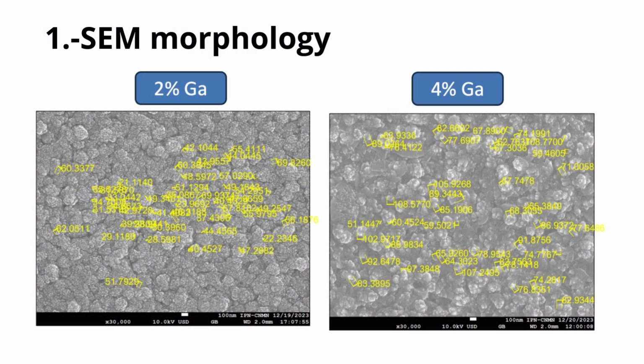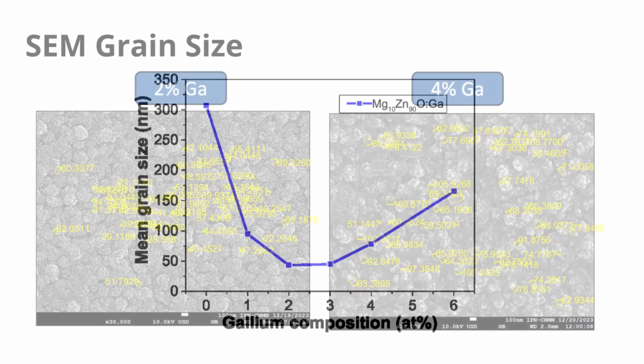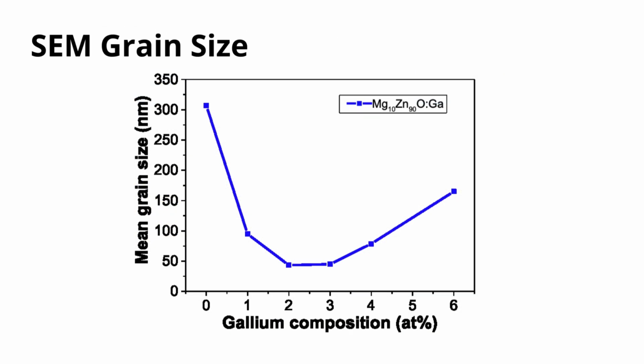The first step of characterization is SEM. SEM morphology. To verify the morphology, a scanning electron microscope, SEM model JSM 7800F JEOL, with the Apollo X10 EDAX detector was applied. The grain sizes were measured to know how this size changed depending on the percentage of gallium doping. As you can see, the behavior is non-monotonous with the minimum between 1 to 2% of gallium.